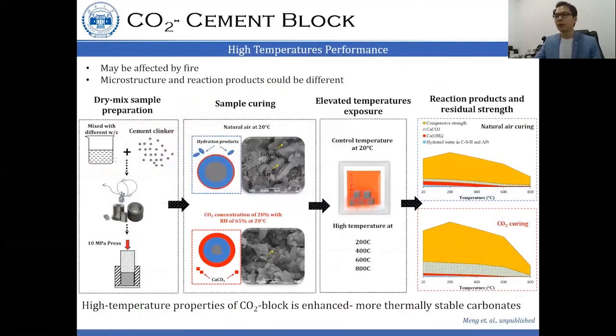And as the CO2 cement block could be a new potential building material, the risk of exposure to fire could be increased. So additionally, we know that the microstructure or reaction products of CO2 block is totally different from the sample with conventional natural air curing. So we exposed them to different high temperatures, 200, 400, 600, 800, and we found that the residual compressive strength up to 600 for CO2 curing still remains relatively high and is able to maintain the calcite content until 600. But further increasing the temperature will significantly reduce the strength as well.